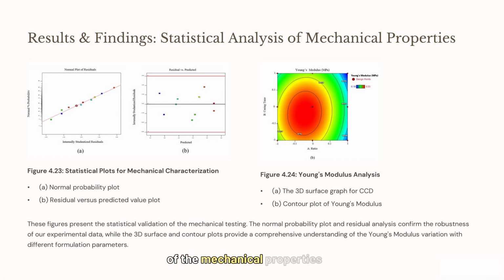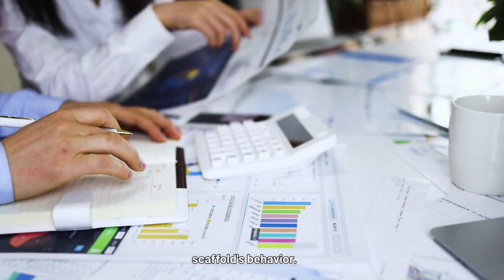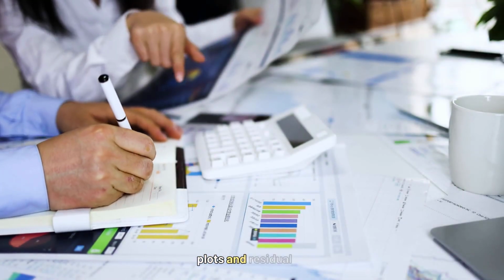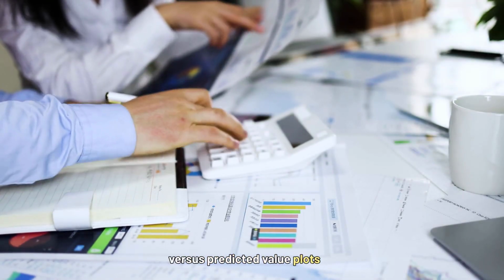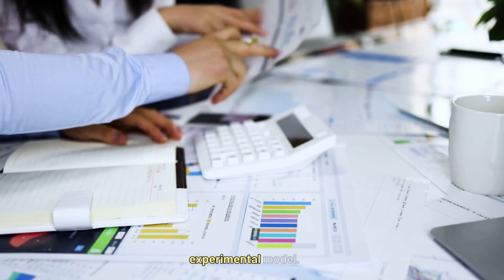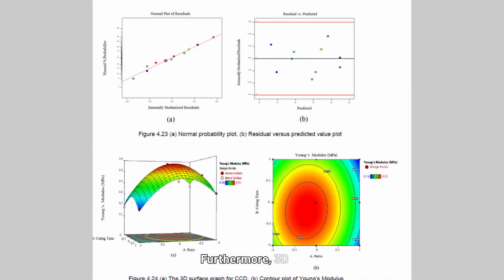Statistical analysis of the mechanical properties provided deeper insights into the scaffold's behavior. Normal probability plots and residual versus predicted value plots confirmed the validity of our experimental model. Furthermore, 3D surface and contour plots of Young's modulus clearly illustrated the optimal processing windows for achieving desired mechanical characteristics, guiding our material optimization efforts.